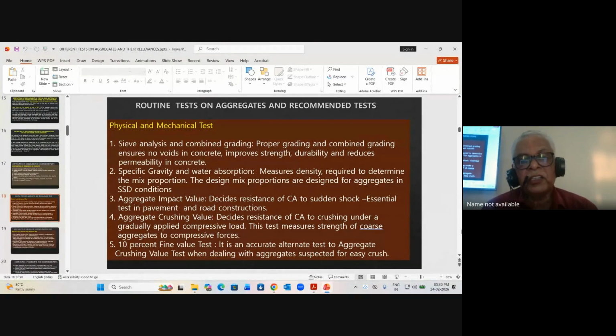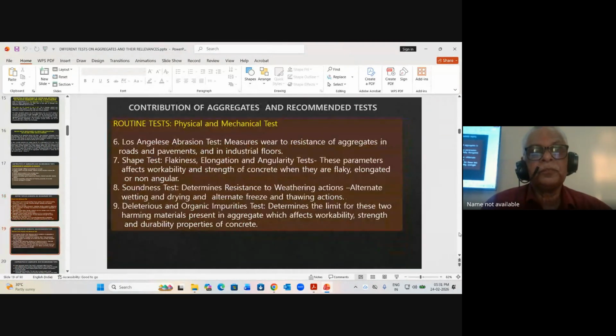Aggregate crushing value decides the resistance of coarse aggregate to crushing under gradually applied compressive load. This test also measures the strength of coarse aggregate to compressive forces. The 10% fine value test is an accurate alternate test to the aggregate crushing value test when dealing with aggregates suspected of being easily crushed under small loads.